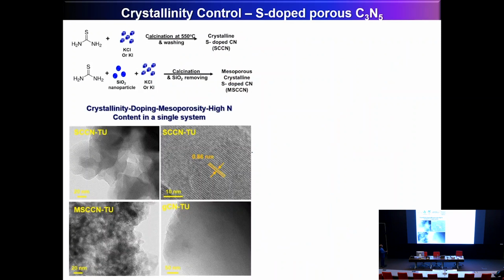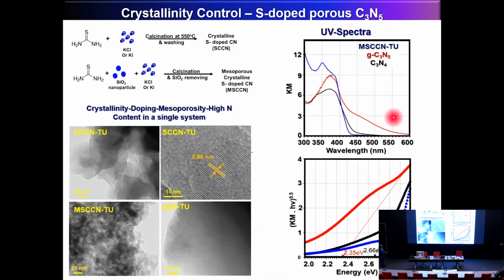And then we also made carbon nitride with the normal templating strategy and the non-templating strategy with the crystalline carbon nitride framework by using potassium chloride or potassium iodide as a salt. To make a mesoporous crystalline carbon nitride, we use thiourea and silica nanoparticles, and we could get mesoporous crystalline carbon nitride after the calcination and the silica removal, as you see here, right? So band structures didn't change much. It's almost similar to that of the bulk carbon nitride. It's in the range of 2.35 to 2.66 electron volts.